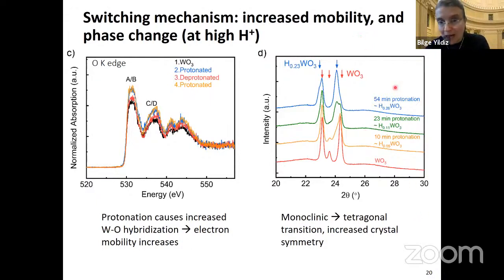And furthermore, at high hydrogen concentrations, we see a transition from monoclinic to tetragonal structure, which comes with increased crystal symmetry, which can also contribute to increased mobility.